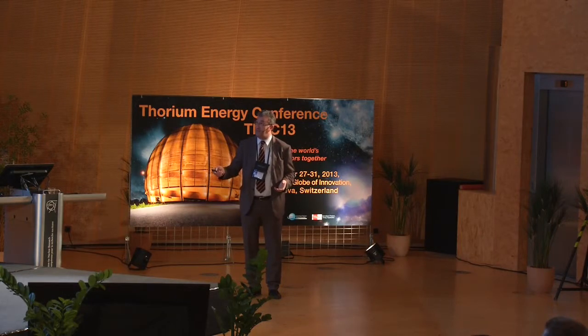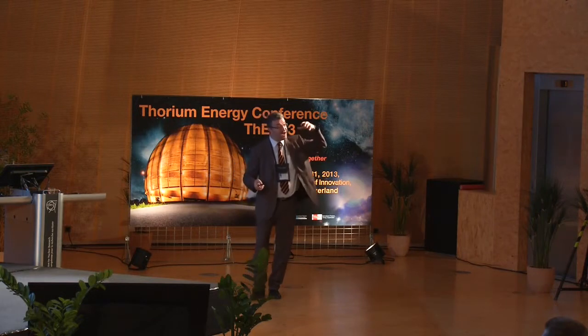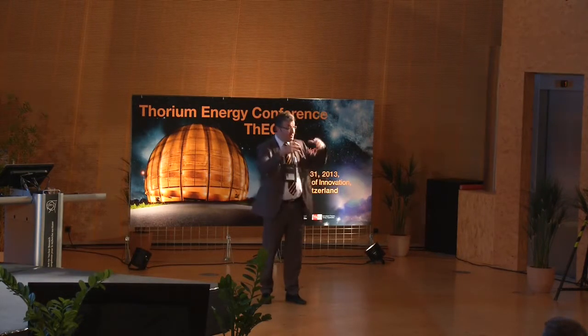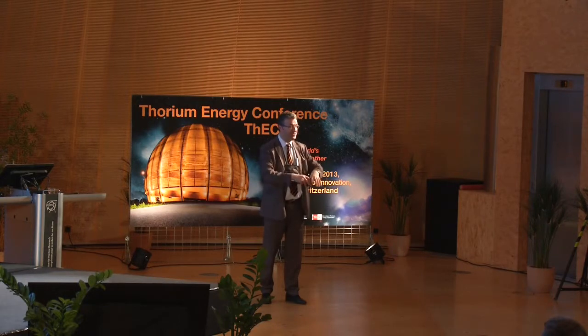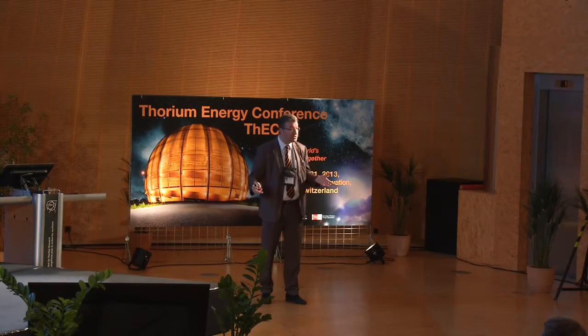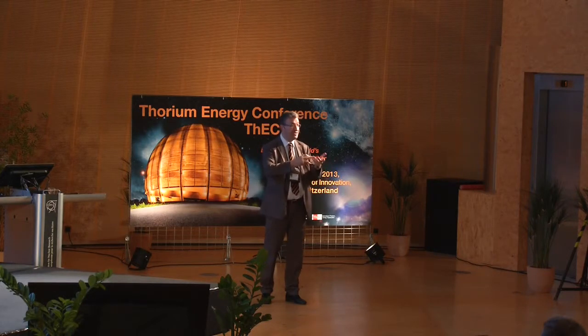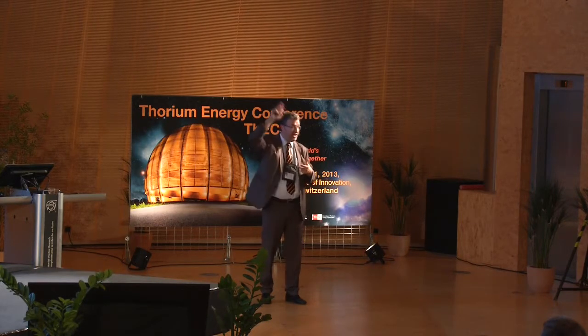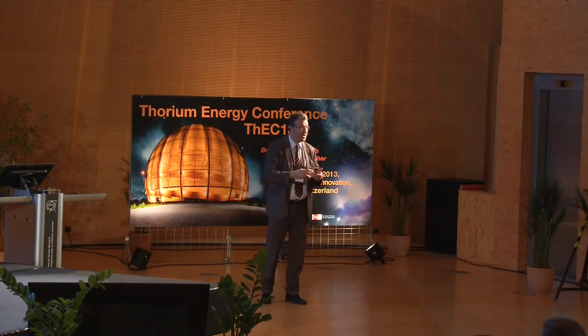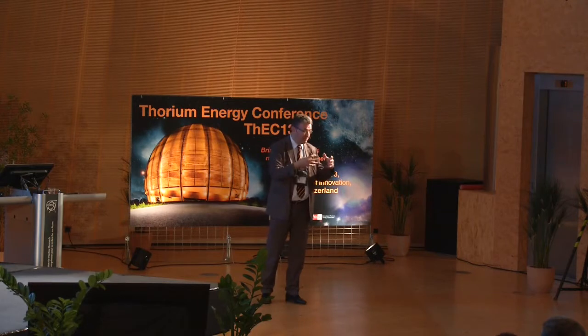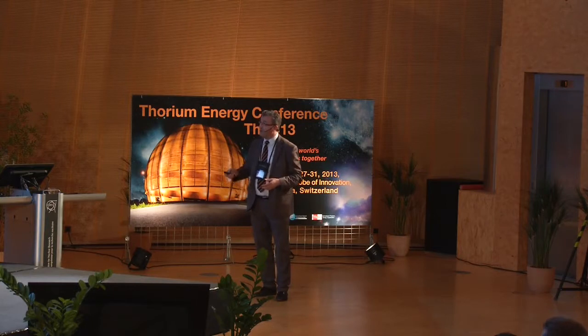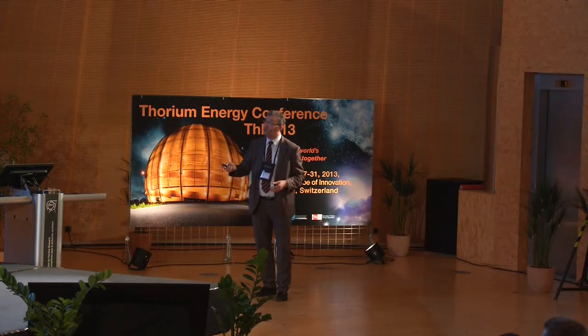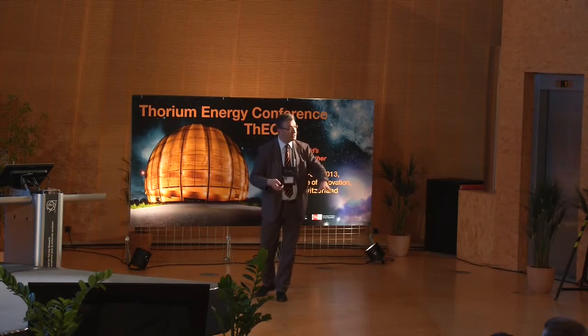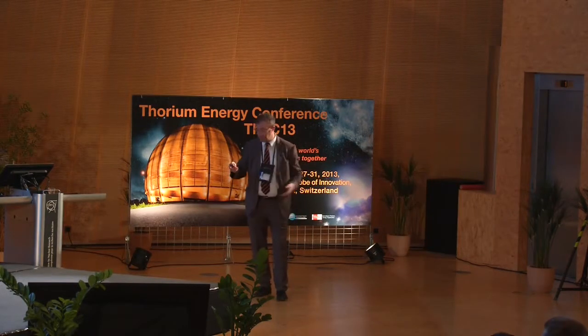And what is the advantage of those particular 7 positions? They are accessible through the lead. This means that we can put conditions of irradiation which are completely independent of the condition of the reactor. I can change the fluid there. I can change the temperature as I want. I can have a separate control of the temperature. And this is then giving a very big flexibility for these irradiation channels. And the other ones are also positioned to make irradiations, but at the conditions of the reactor in terms of temperature.